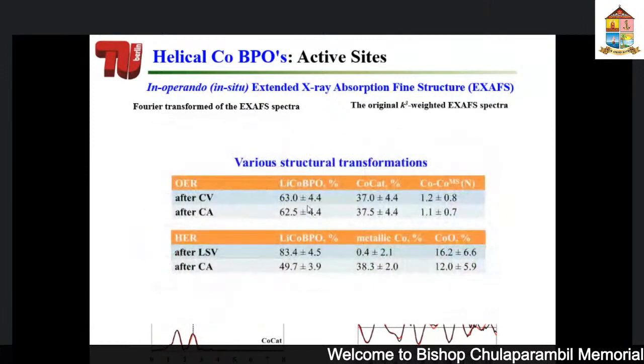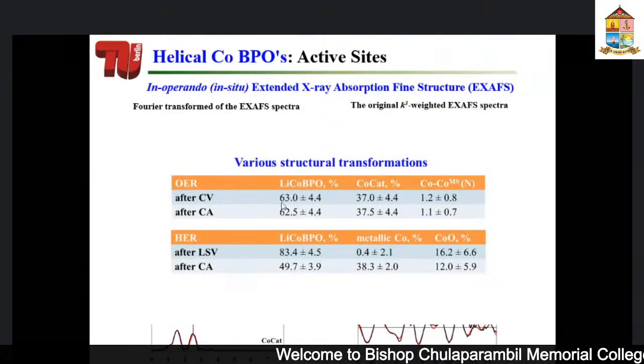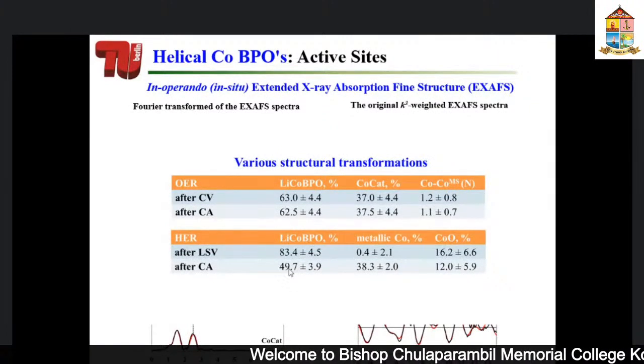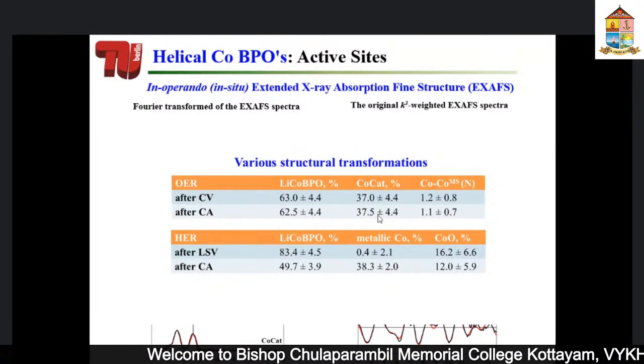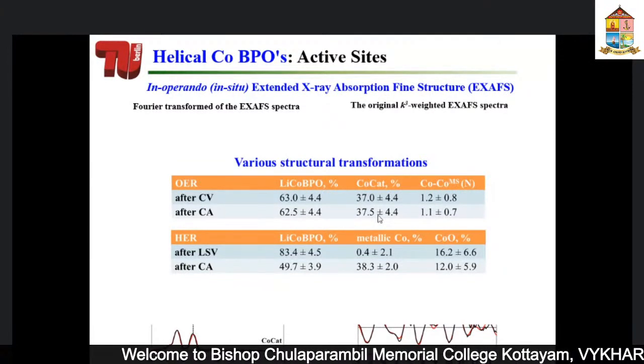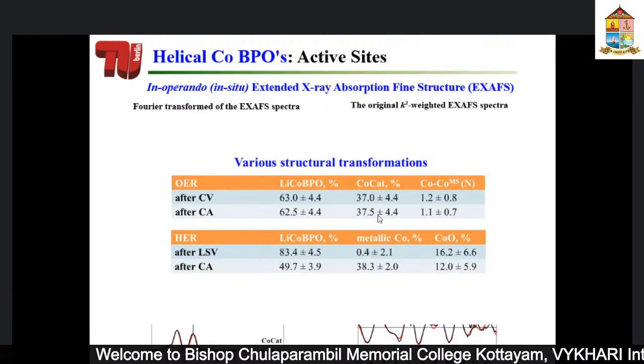Okay, to cut the story short, what do you have? Once you have your structure, you retain 63% in the case of the oxygen evolution reaction, and let's say 49% of your structure is retained in the hydrogen case, but the rest changed on the surface. That means you don't have a stable catalyst, one that changes significantly during your catalysis.